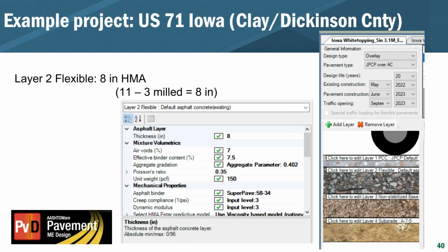And as Chris and Ben had implied, it could be up to 3 inches milled off depending on the profile. And so we entered in 8 inches. For the most part, I did use the defaults, although I did enter the air voids, which if you remember was 7% and 7.5% effective binder.